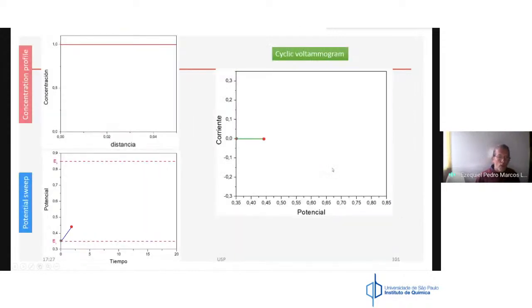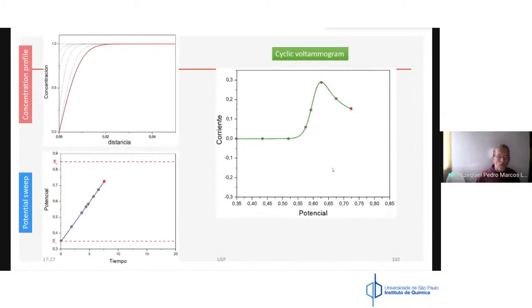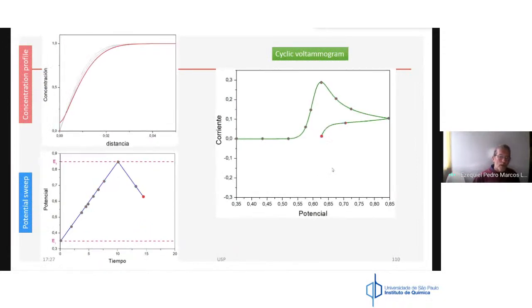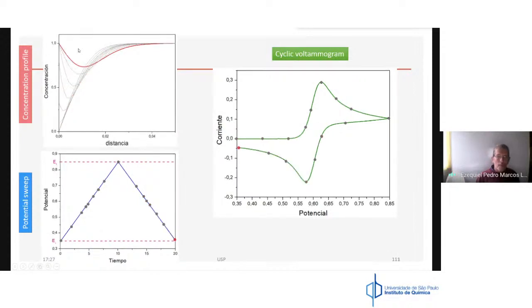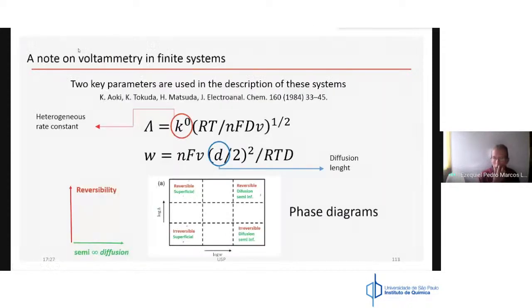And we constructed voltammograms. You sweep the potential, you get the voltammogram, and you can follow the evolution of the concentration as a function of time. We did this for a finite system, and in the case of a finite system, you get two parameters which represent the behavior of the system concerning reversibility. On one side, there is one parameter that contains the heterogeneous rate constant, and there is another parameter that contains mainly the diffusion length of the system.